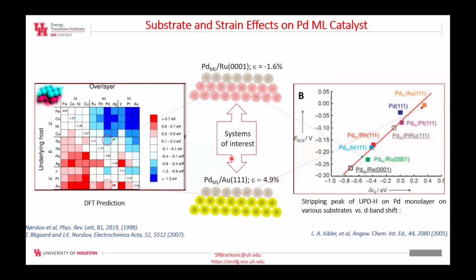Therefore, if the substrate has a bigger lattice than the palladium as an active catalyst for hydrogen water electrolysis, then the d band or electron density on the surface is shifted upward, meaning more energy in the electron d band is available for overlap, and therefore the catalyst is more reactive. If the strain, because of the epitaxial relation, is negative or compressive, then the activity of the catalyst is suppressed.